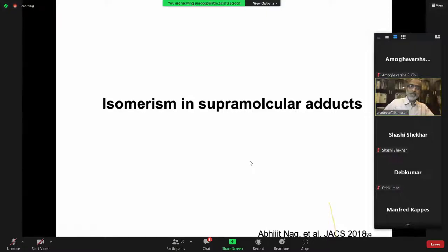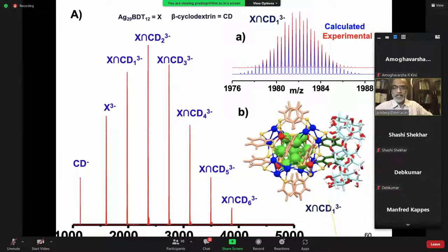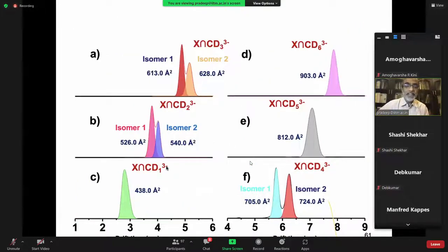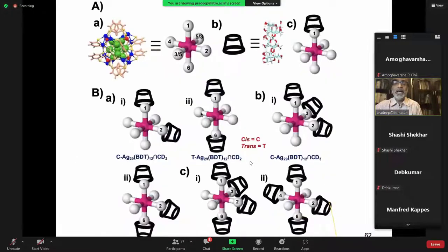Another interesting aspect is isomerism in these cluster systems. So here is a cluster, and this is called BDT, benzene dithiol, and two of them are sitting on this silver 29 surface close by. You can put a cyclodextrin on it. In fact, six of them can be put, and that covers the surface completely because there are 12 BDTs present. But if you take this adduct with one CD, it has only one isomer, whereas two has two isomers, three has two isomers, four has two, five, there is no isomer, six, there is no isomer. And that is because you have the structural possibility in the system.